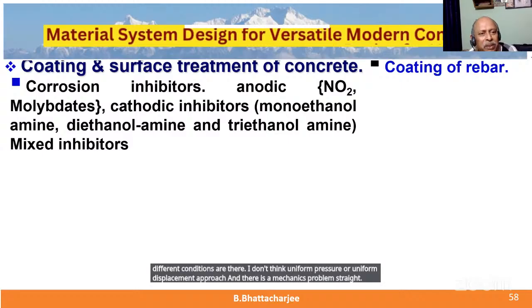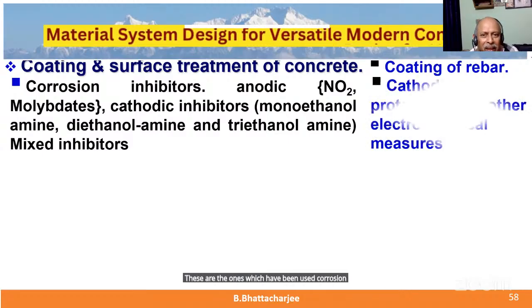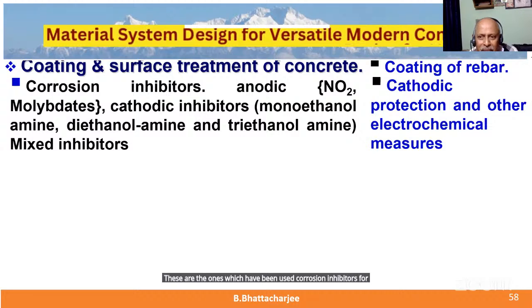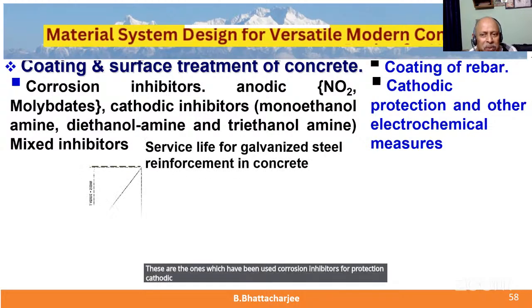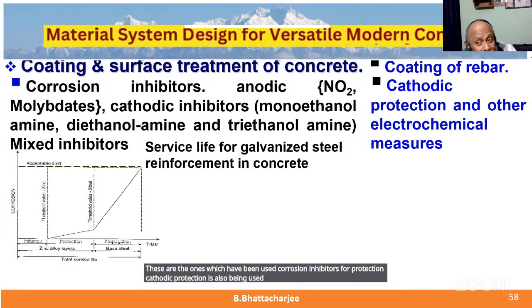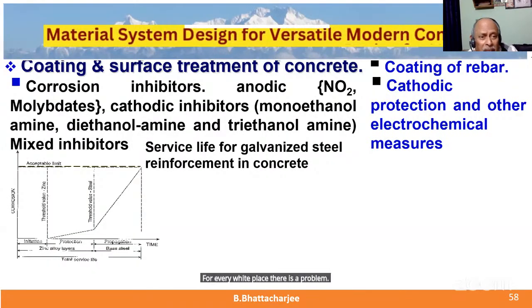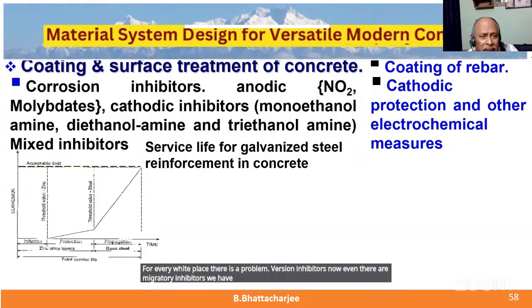These are the ones which have been used: corrosion inhibitors for protection. Cathodic protection is also being used in marine structures where it is very important. If you know the place where you want to apply this, it's fine, but if it's a very wide area, there is a problem. For corrosion inhibitors, there are now even migratory inhibitors. We have done some work on that. I didn't put it here because it was already becoming too long.